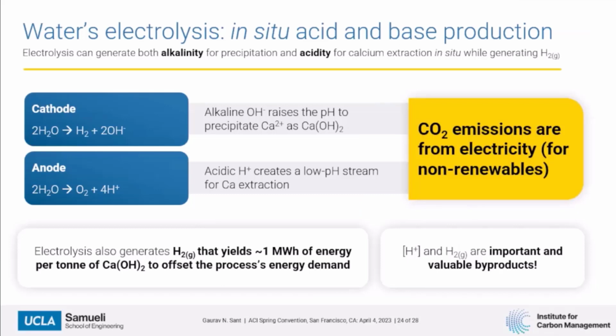So the approach that we took to this is really based on water electrolysis, right? So you take water, you split it, run a current through water. Essentially, at the cathode, you end up producing hydrogen and hydroxyl ions, and at the anode, you end up producing oxygen and protons, right? Acidity. Why is this important? The hydroxyl ions allow you to increase the pH of the solution and precipitate calcium hydroxide. The acidity allows you to dissolve rock, right? So in effect, you can use just stuff that you get out of water combined with electricity to be able to produce, as an example, calcium hydroxide.